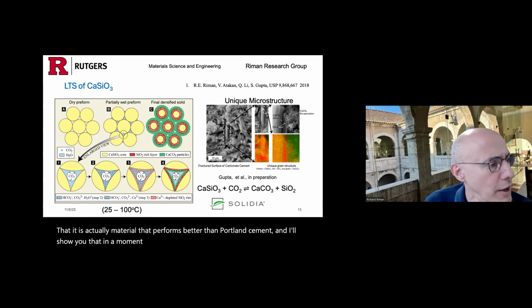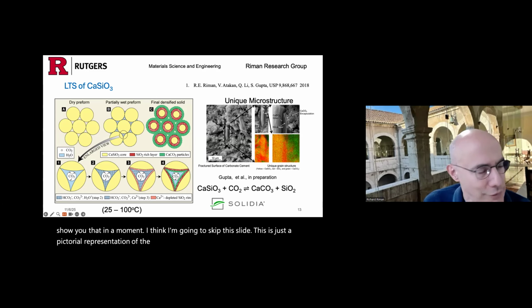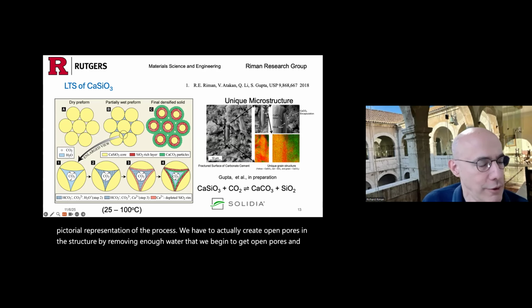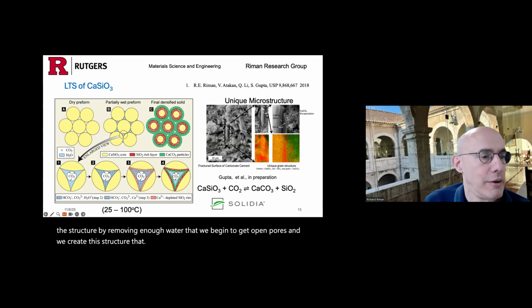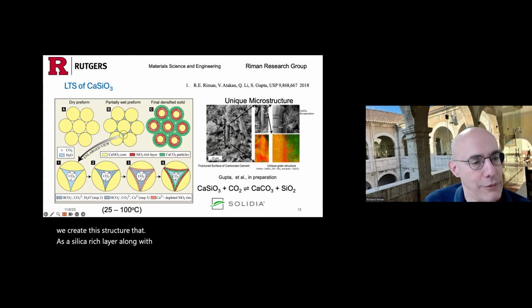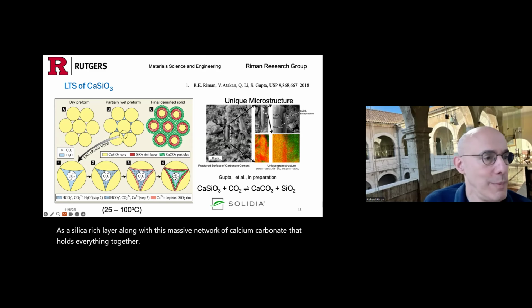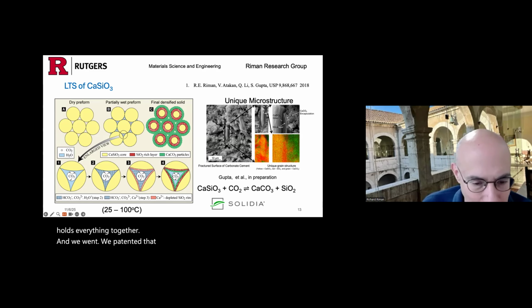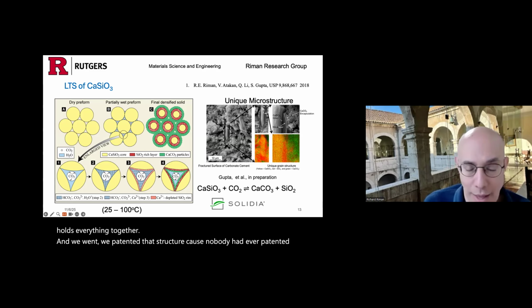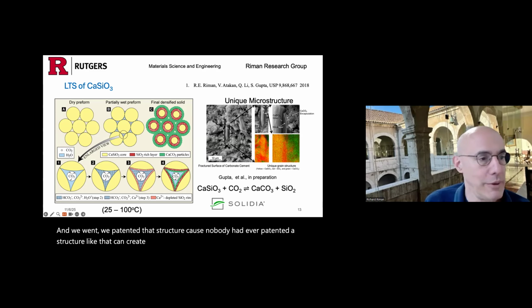I think I'm going to skip this slide. This is just a pictorial representation of the process. We have to actually create open pores in the structure by removing enough water that we begin to get open pores. And we create this structure that has a silica-rich layer along with this massive network of calcium carbonate that holds everything together. And we went and we patented that structure because nobody had ever patented a structure like that that can create mechanical stability. So we call this process low temperature solidification or LTS.